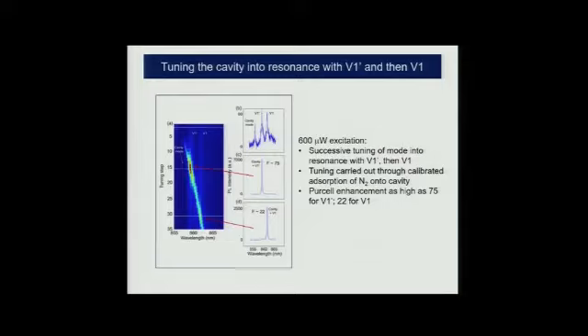But now let me look, as a function of wavelength, let me tune the cavity. Originally the mode is here. Let me bring this mode into frequency resonance first with V1 prime and then V1. How do I do that? The cavity response is a function of its geometry. If I change its geometry ever so subtly, such as by adsorbing monolayers of gas, then I change the frequency response of the cavity. And indeed, this is what these traces show as you go through different tuning steps from 0, 10, 15. You begin to redshift the resonant mode of the cavity to longer and longer wavelengths